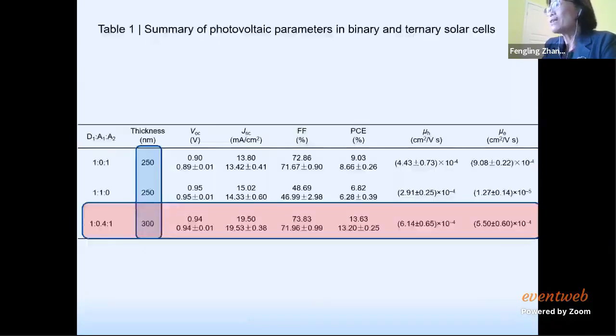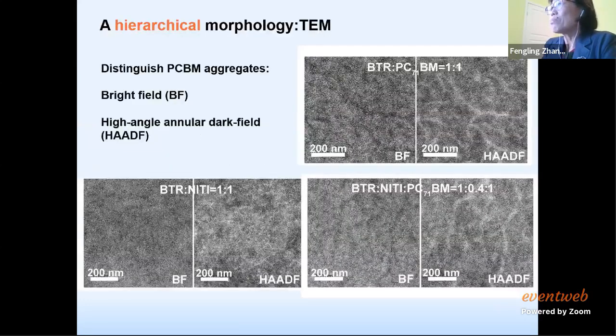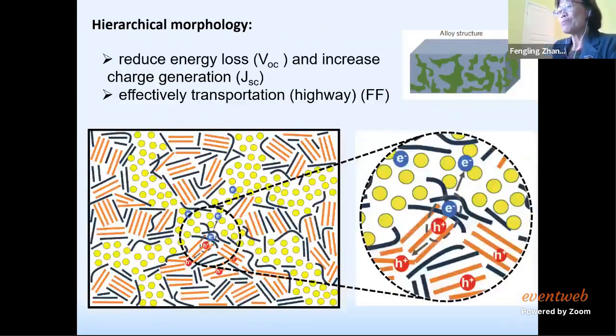So we tried to understand the role of the fullerene acceptor in the device. We imaged the bulk heterojunction, and if we compare binary and ternary, we see the PCBM actually forms clearly like a highway for the charge transport. Here we suppose PCBM is like a highway, and the non-fullerene acceptor helps to separate the exciton, then gives the electron to PCBM. So PCBM takes the electron away. With this ternary, we synergize the two acceptors. They play different roles, one for charge generation, one for charge transport.